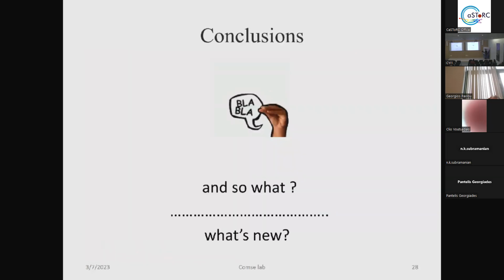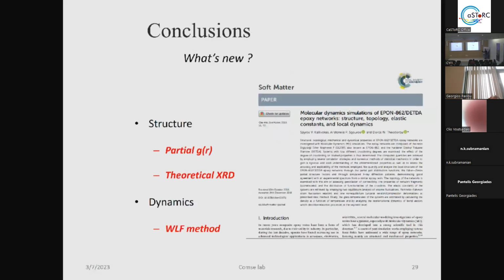So, what's new at this point? For the first time in these systems, the partial g(r), theoretical XRD and the glass transition temperature through the WLF method were calculated. And also a more accurate way to calculate the mechanical properties through the Parrinello-Rahman method. And that leads us to this Soft Matter publication in 2019.